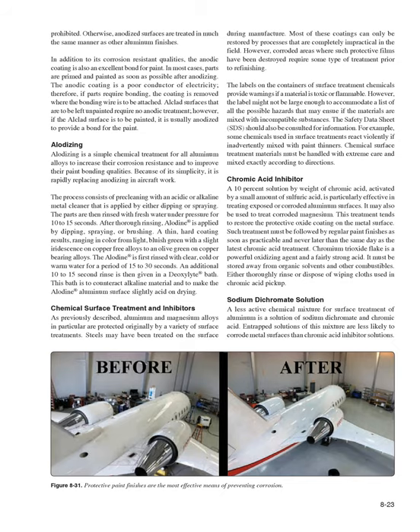Chromic acid inhibitor, a 10% solution by weight of chromic acid, activated by a small amount of sulfuric acid, is particularly effective in treating exposed or corroded aluminum surfaces. It may also be used to treat corroded magnesium. This treatment tends to restore the protective oxide coating on the metal surface. Such treatment must be followed by regular paint finishes as soon as practicable and never later than the same day as the latest chromic acid treatment.